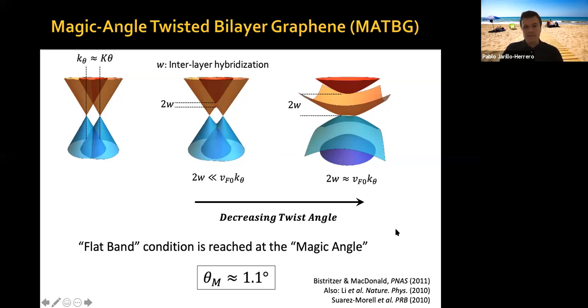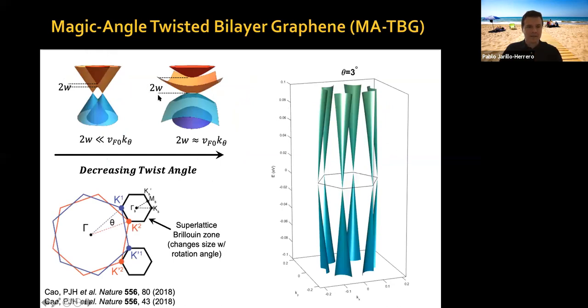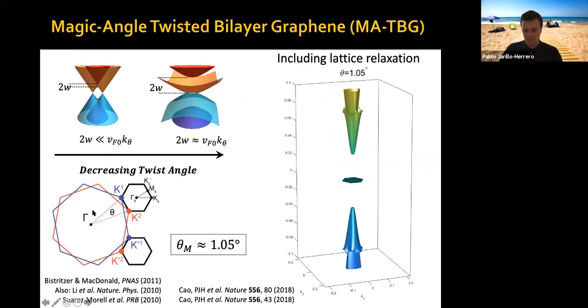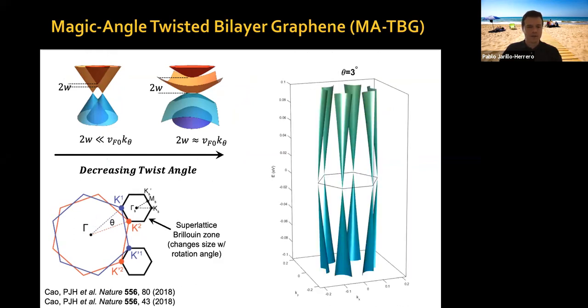Now, this is a schematic cartoon of how this whole process happens. Let me show you an actual video of the electronic structure as a function of angle, okay? So here you have the two reciprocal spaces of layer one and layer two of graphene. If you join the corners of the Brillouin zones, then you get the superlattice Brillouin zone, sometimes called the mini Brillouin zone. You can see it's much smaller because you form a long-range moiré pattern in real space, which means in momentum space you have to Fourier transform.